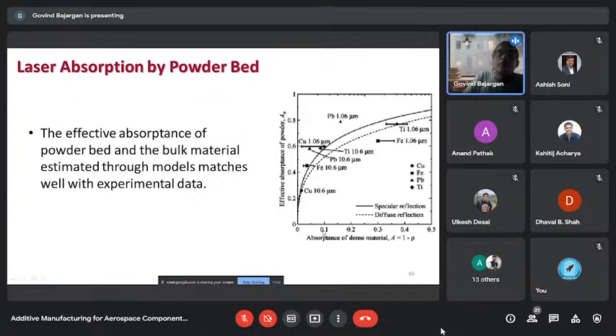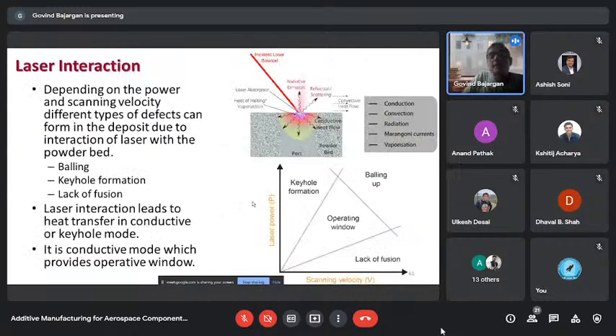So we saw one advantage of using a powder bed is that the absorption of the laser is far better, and it is good for fiber laser. How does the laser interact with the powder? Depending on the power and the scanning velocity, different types of defects can form in the deposit, and it all depends on the interaction of the laser with the powder bed. It can be balling, keyhole, or lack of fusion.